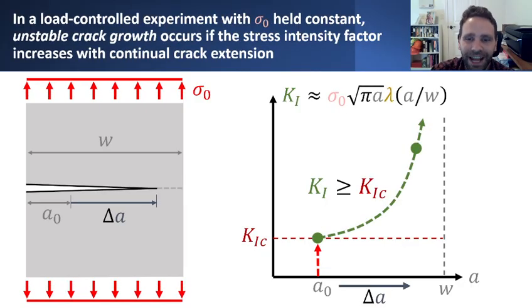Now, consider what happens if we ramp up that value of stress all the way up to the point where now we have K1 equals K1C. Right at this instant, let's say, we ramp up sigma naught such that K1 equals K1C, exactly, which is corresponding to this point on this diagram. In that scenario, clearly, we have that K1 equals K1C, which means that crack extension will occur. When crack extension happens, we'll go from a crack that was originally of size A naught to now a crack that has size A naught plus some delta A.